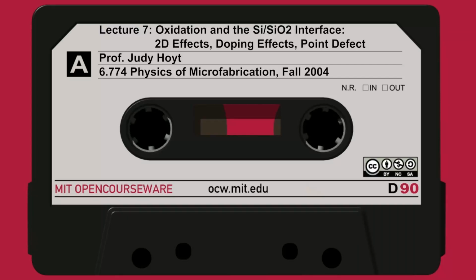So it has to do more work on the oxide above it than it would have to do on a planar surface, because it's really confined all the way around. So the oxide on the curved surface has got to flow in order for this to happen. You have this solid material, this glass, that has to essentially flow. So there's a certain amount of stress buildup as a result of that.